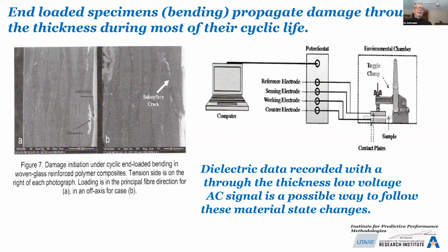So he did that. And as a matter of fact, on the right-hand side, he stopped the test from time to time, put the specimens in a chamber and measured the dielectric performance. And in some cases, he introduced a material that would increase the dielectric response if it diffused into the crack, an iodine material. It would have an even higher dielectric response than the air or moisture that might be there otherwise. So he was able to follow quite well this fracture plane development, and he got some interesting results.